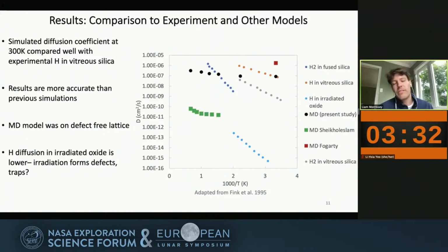But one thing that we did find interesting is that if you look at the bottom of this plot in the light green, you can see that H in irradiated oxide had a far, far lower diffusion rate. And it's important to note that our MD model was done on a defect-free lattice. So this flagged to us that we wanted to know what's going on here, because we know that H diffusion in irradiated oxide is lower, and we know that irradiation forms defects, so we wanted to see whether this was traps.